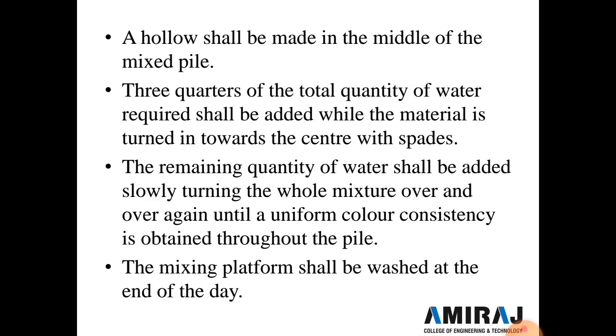Now a hollow shall be made in the middle of the mixed pile, and 3/4 of the total quantity of the water required shall be added while the material is turned from the outside toward the center with a spade. The remaining quantity of the water shall be added slowly, turning the whole mixture over and over again until a uniform color and consistency is obtained throughout the pile, and the mixing platform shall be washed at the end of the day.